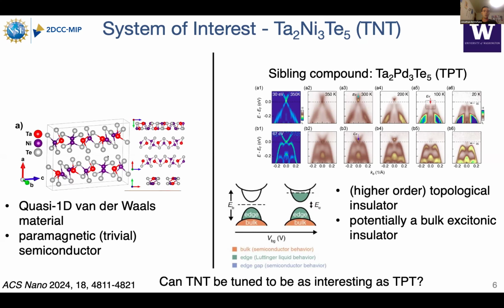And so you might ask, why are we interested in this material? It turns out that the very similar sibling compound, where if you remove the nickel and throw in palladium to form tantalum palladium tellurium 235, or TPT, is actually a very interesting material. It's potentially a higher order topological insulator. People have observed that in experiment. And then also people have seen signatures of it potentially being a bulk excitonic insulator.